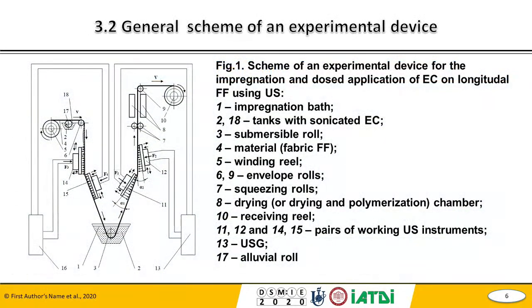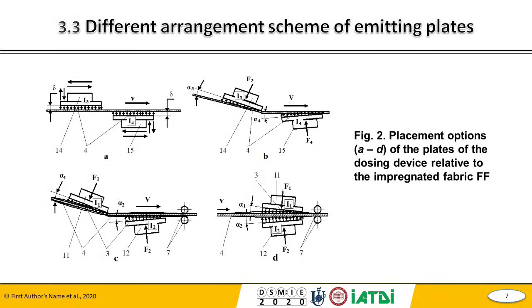On the next slide, we can see the general scheme of the experimental device for ultrasonic impregnation and dosing application. This machine consists of the impregnation bath, tanks for sonicated epoxy composition, submersible roll, winding reels, envelope rolls, squeezing rolls, a drying chamber with several temperature zones, for example from 100 to 130 centigrade, then receiving reels, ultrasonic instruments, an ultrasonic generator and rolls. The next slide presents different arrangement schemes of the emitting plates of the dosing device relative to the impregnated fabric filaments. Please, next slide.